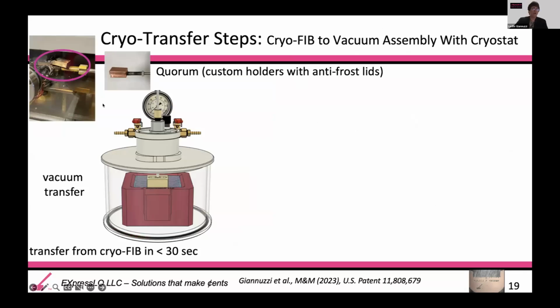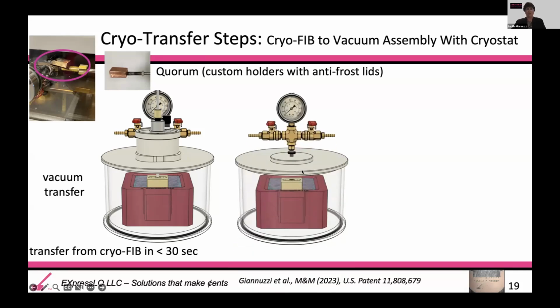Okay, so we can make our FIB specimens that are very similar to our conventional ambient FIB sample under cryo mode. We developed a special cryo holder that can go on top of, in this case, a Quorum dovetail that has an anti-frost lid. And when we pull it out of the prep chamber, we developed a cryostat inside a vacuum transfer system. So we can take the cold specimen, put it right into this little cryo jacket, and then remove the holder, put a lid on it, and pump vacuum, so that we can take it into our cryostat.